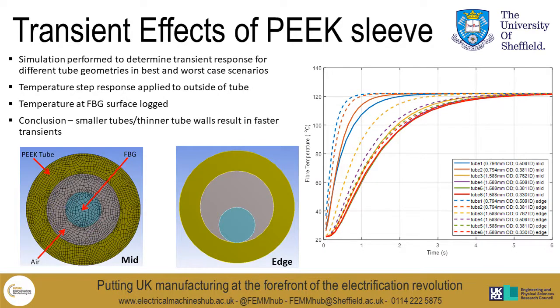This slide shows some modelling which was done to determine how much the transient response of the FBG would be affected by using different sized PEEK sleeves. You can see from this slide there were two different models considered, which can be thought of as the best and worst cases in terms of positioning of the FBG within the sleeve. The one which I've referred to as the mid model on the left has the FBG perfectly centred in the tube with a cushion of air all around it, whereas the edge one is the case where the FBG is resting on the edge of the tube. In reality, the situation is more than likely somewhere between the two. As you can see from here, basically, the larger the tube which is used, the slower the transient response.